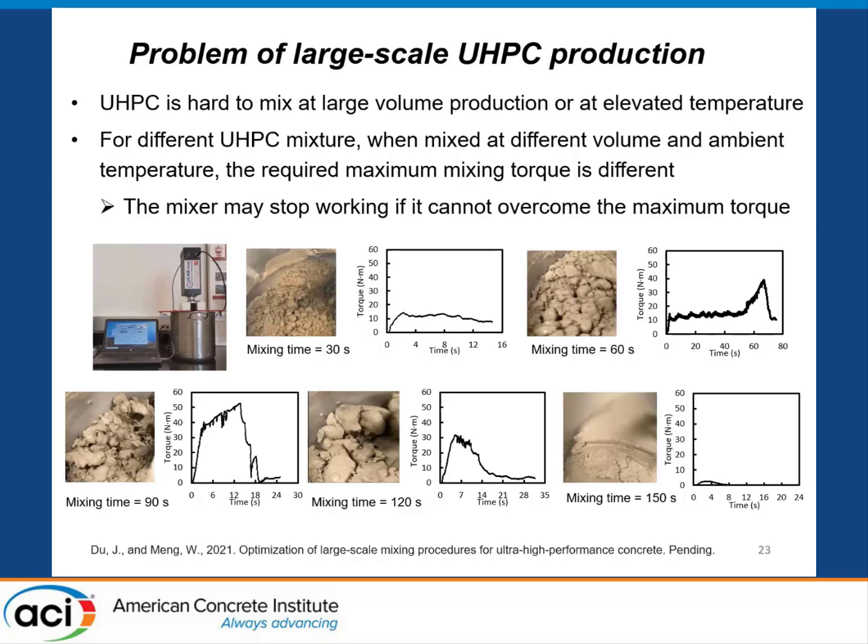From our preliminary studies obtained from the ICAR rheometer, we found that at the beginning of the mixing stage, the mixture is powder-like, so it's easy to mix, because the required mixing torque is low.